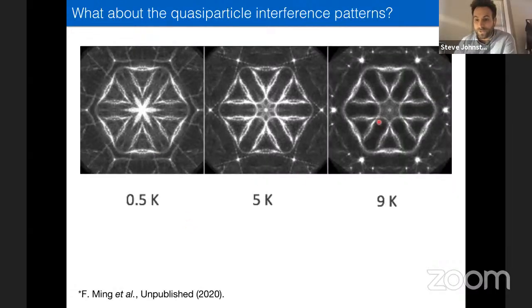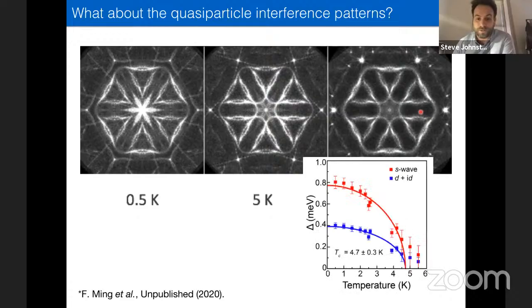And if you go well above TC, they disappear completely, right? So again, remember, this is well below TC. This is just above TC, and this is well above TC. Those star patterns are disappearing. So they seem to be really tied to the superconductivity itself. And again, I'll remind you, this 5 Kelvin is right around the region where we had some evidence that there may still be some superconductivity, possibly fluctuating superconductivity. We're not really sure.